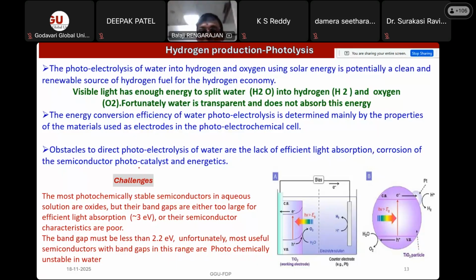All over the world, R&D is going on to get the maximum efficiency, because when you convert photons into electrons and electrons into hydrogen, the overall efficiency is close to 9 or 10%. If you could identify a material which can do both jobs and get 9 to 10% efficiency, then it is a technological breakthrough. So far, TiO2, the titanium dioxide based material, is fairly good, as it does the dual job of converting photons into electrons, electrons into hydrogen, and it is stable.